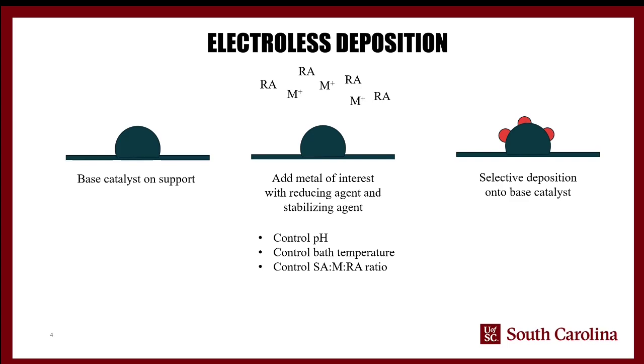And so the way that we've worked to get around this is through a technique developed by the Monnier group called electroless deposition. And the basic idea here is you start with a support and you have some base catalyst on this support. In this case, we used palladium nanoparticles on carbon. And I believe this is actually a commercial substrate. So it's 5% palladium on carbon. And the palladium itself is almost like a target for the reduction reaction. Although the palladium does not carry out the reaction, it acts as a selective substrate.